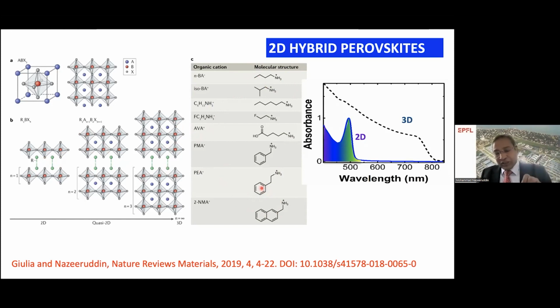By using this particular cation and other cations that go into the three-dimensional perovskite, now compare the absorption spectral properties. With the three-dimensional perovskite, where the cation goes into the cavity, we have the spectral response going from 800 nanometers all the way across the whole visible spectrum. On the contrary, if we change the small cation and use some of these larger cations, we form a two-dimensional perovskite that has a very small absorption in the visible region. However, three-dimensional perovskite has less stability compared to the two-dimensional perovskite.